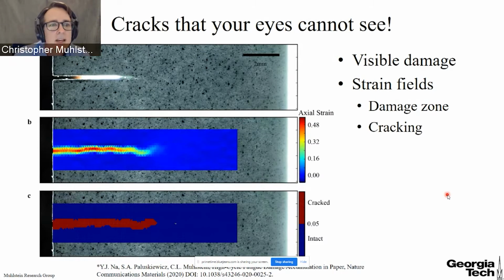But in our case, we cut them and then we pull on it, and ahead of the notch, it's backlit and frontlit, you see all these little fibers stretched across. And the question becomes, with a material like paper, where the network is stretched across that crack, maybe it's broken, but you can't tell anymore. And this is a byproduct of the fact that it's a fiber network structure and the way that light interacts with those fibers.